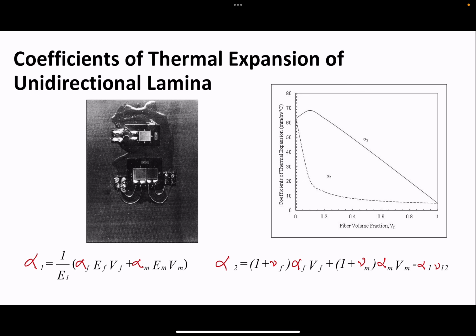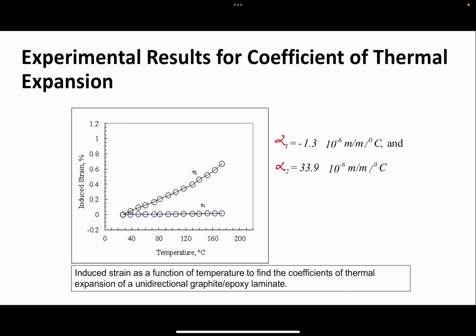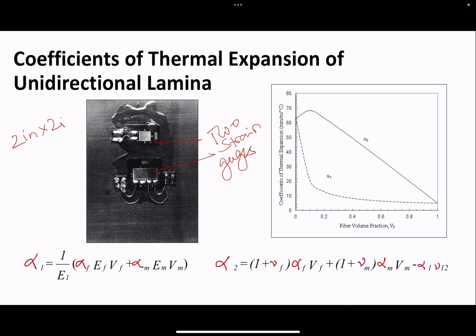For thermal expansion, of course, you mount strain gauges on the specimen. Let me see if there is a particular standard specified in your book. No, the standard is not given. But you measure the dimensional changes, and that is why you have two strain gauges. The test specimen is a 50 by 50 mm, or 2 inch by 2 inch specimen, of 8 plies of unidirectional composite. And then 2 strain gauges are placed perpendicular to each other. So you can see one is in the 0 degree and one is in the 90 degree.